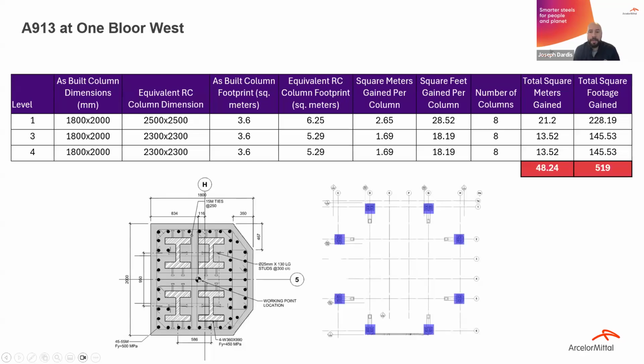And Daniel did show this briefly on the size of the mega columns, the initial solution, which was reinforced concrete, versus the mega column solution. And that actually brought a lot of square footage back to the project. So just the difference in size of the footprint of the mega column versus the reinforced concrete column isn't something to ignore. And I think that is often ignored, and we don't take that into consideration. So if we just look at the first few levels, we gained about 519 square feet back just from that column footprint. Now, you might see that number and say, okay, that's maybe the size of a studio apartment.